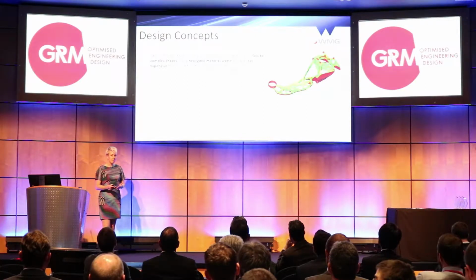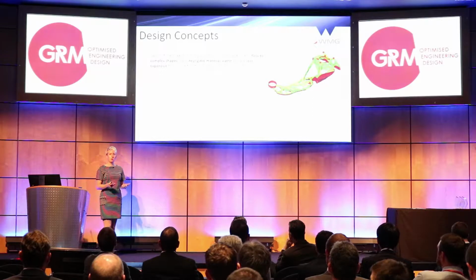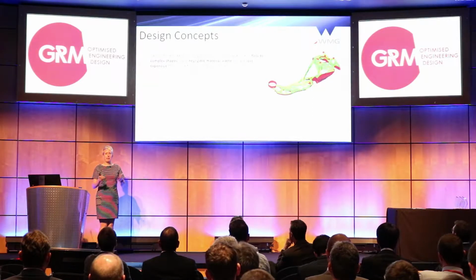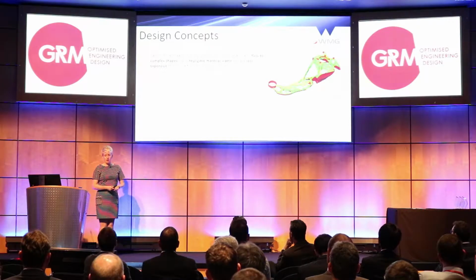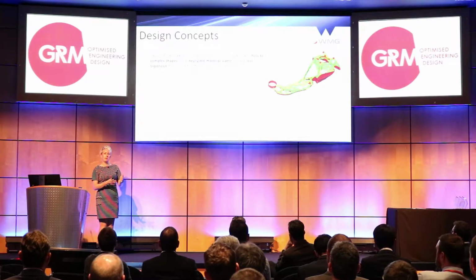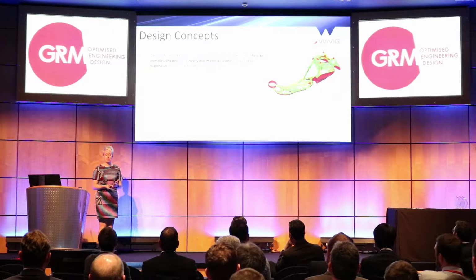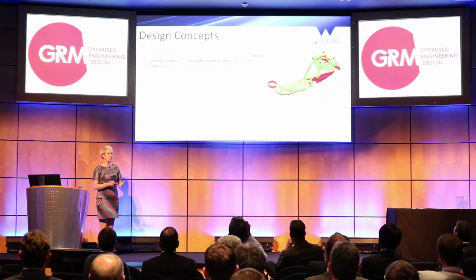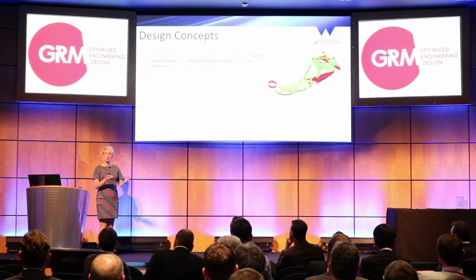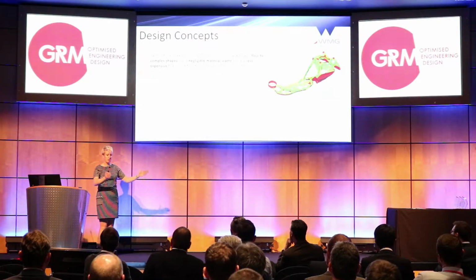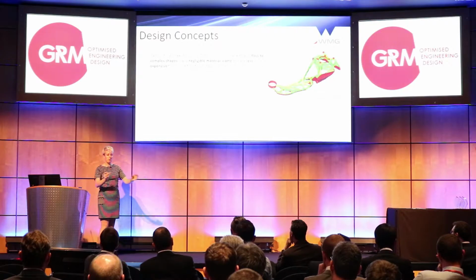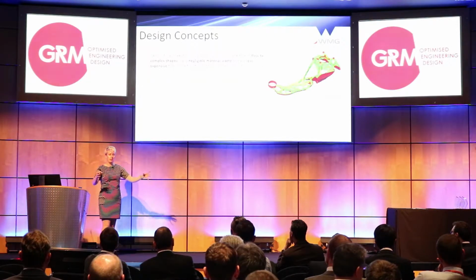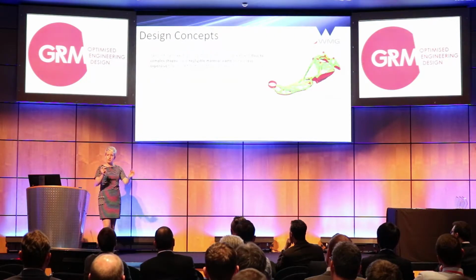More innovative SMC materials that are currently on the market now are called carbon SMC. So they use carbon fibres. So they're more expensive, but less expensive than pre-pregs. But they have the ability to flow and meet quite complex geometry requirements that you can't always achieve with traditional pre-preg materials. And also, on top of this, they don't have any waste. So all the waste that you get when you're cutting off a sheet, this time, because it moulds and flows, you can put any shape in and just fill your mould, and all you're trimming off is a bit of resin off the edge.